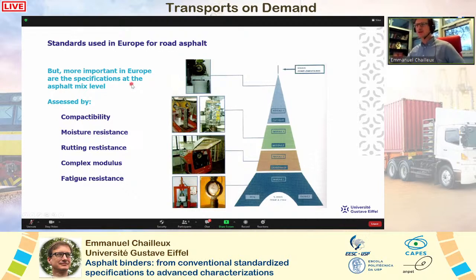for the asphalt mix, specifications are firstly based on the compactability, which is the first step, using the gyratory compactor. Our material has to be compacted easily. Then moisture resistance, using in France the Duriez test. And then rutting resistance, using the French wheel tracking test. And then, if needed for structural courses, for example, complex modulus measured at 15 degrees, 10 Hertz, and also fatigue resistance. But I will not go into detail on this specification at the mix level.